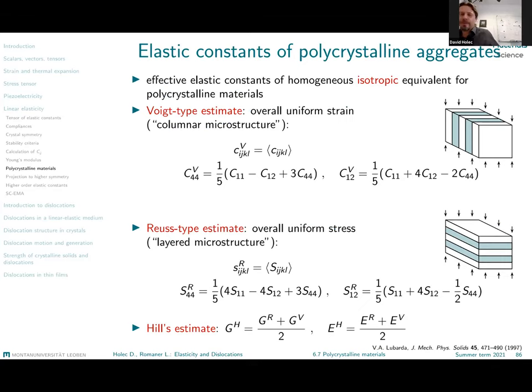Right? Then, in order to provide a single value, because of course, when I go to the lab and measure the Young's modulus or shear modulus of my material, I would have a single value, we simply average those two values, the Reuss and Voigt estimates. The idea behind this is to say, well, those are two extremes and the reality is probably somewhere in between. And this is called the Hill's average or Hill's estimate of the elastic constants. A side note here: for cubic materials, the resulting bulk modulus of Voigt and Reuss is the same and is the same as the single crystalline value. So for cubic materials, there is no difference whether we speak about the Voigt and Reuss values.